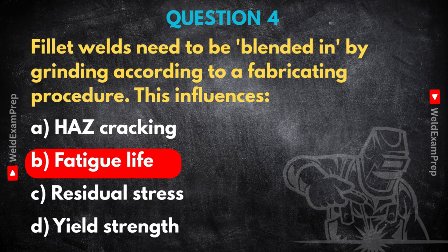Residual stress is the locked-in stress from welding. Grinding can affect surface residual stresses very locally, but the primary intended effect of blending the toe is definitely fatigue life enhancement. And yield strength is just a basic property of the metal itself, not changed by this kind of surface treatment. Got it. So that blending step in the procedure is really targeting long-term durability.